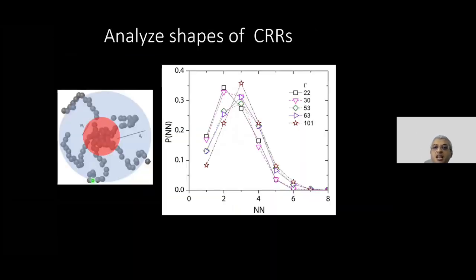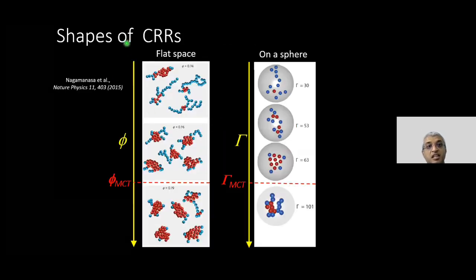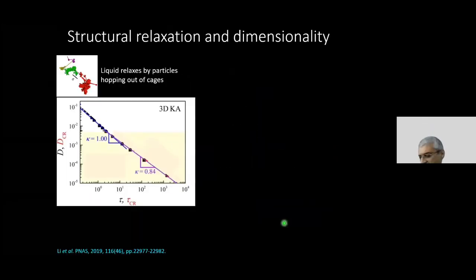We can go to each mobile particle, and if I had a string-like dynamical heterogeneity, it means I have one neighbor in front of me and one neighbor behind me, which means my fast nearest neighbors are 2. But if I had something more compact, I would see something larger than 2. This is for the system on the curved space. This shows the shapes of CRRs in flat space and on a sphere. Just like in flat space, you once again see a compaction of these CRRs on a curved surface as well. We did a bit more, but I've clearly run out of time now.